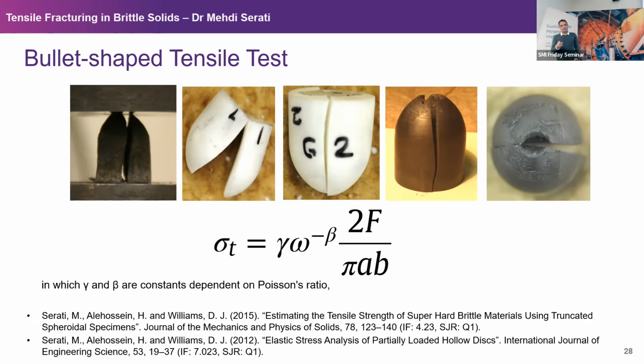But if you're dealing with such a material, and you know that the available testing methods are inadequate to get an estimate for the tensile strength, if you can manage to get a bullet shape and you measure the geometry and the force at failure, you can use this expression to measure the tensile strength. Guess what? Again, it was what I proposed, and the fantastic team that I've been working with. We use this method. We realized that yes, the tensile strength that you get for diamond composite was overestimated.